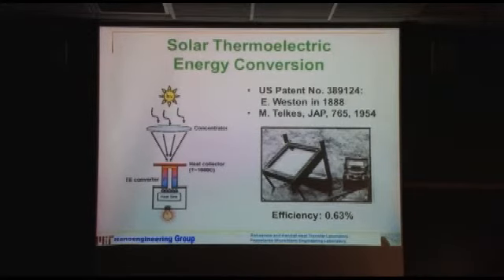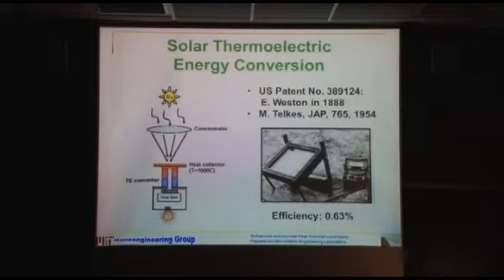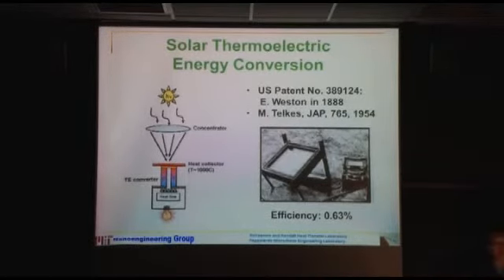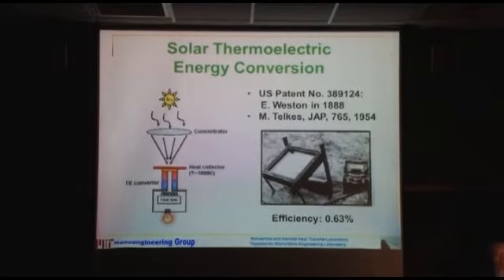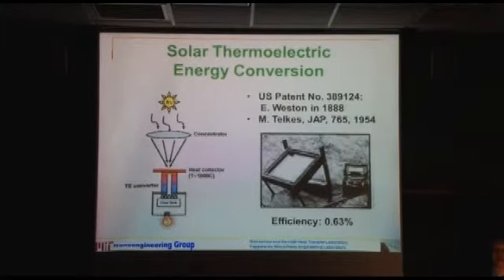So now let me come to solar thermoelectric energy conversion. And basically, now we have the idea, if I can create a temperature difference across the solid state material, I'll be able to generate voltage and generate the power. So if you check the history, in fact, this idea was even first patented in 1888. And at the time, they had very poor material. And in the 1950s, there was an experiment done by Maria Telkes, and she demonstrated you can get about 0.6% efficiency. And that was about the same time as the solar cell, the photovoltaic cell, was invented. And the photovoltaic cell won, and that field has been steadily making progress. And this has stayed at this number since the 1950s, really low progress.